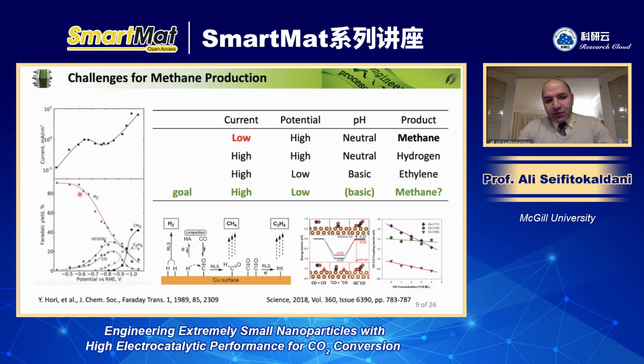At low potential, we see that hydrogen is the dominant product in terms of selectivity. But by increasing the potential, we can also increase the obtained current density, and then we can switch to produce ethylene or methane, but it also depends on the electrolyte that we use. This is represented again in neutral electrolyte, and you see that we can achieve methane, but at very low current density, around 10, 20 milliampere, which is not, again, industrial level.